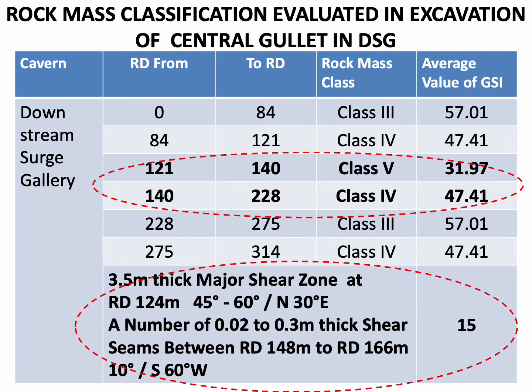Besides a 3.5 meter thick major shear zone at RD 124 meter with an inclination of 45 to 60 degree with a rotation of north 30 degree east, and also a number of other 0.02 to 0.3 meter thick shear seams that existed between RD 148 to 166 meter with inclination of 10 degrees and orientation of south 60 degree west with the geological strength index of merely 15 were present in these reaches.